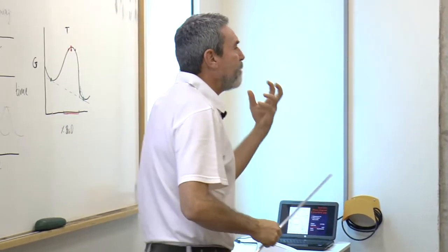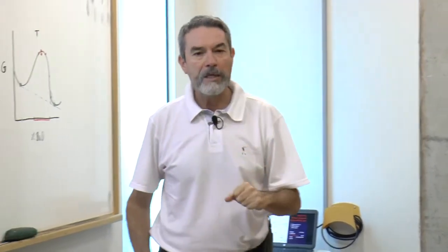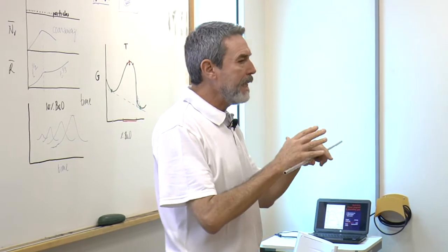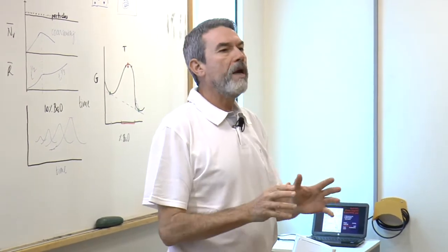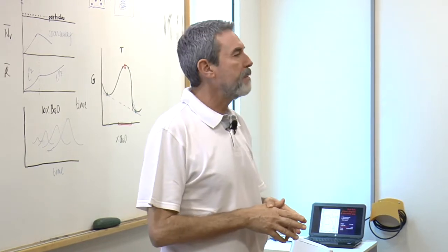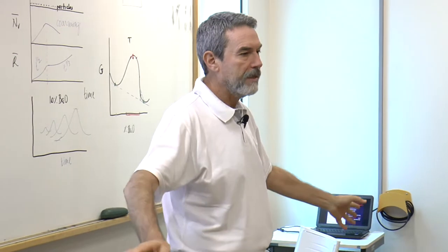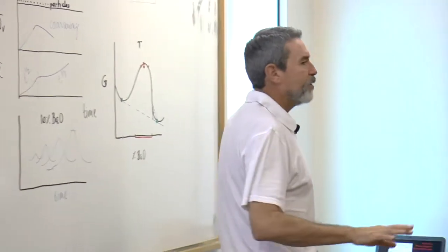So there is no thermodynamic barrier. This is the concept of spinodal decomposition. Any fluctuation that takes place in the system will propagate. It's spontaneous. You cannot stop it.